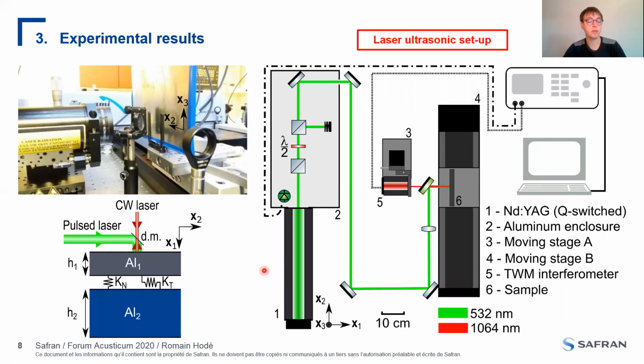To carry out the measurements, we have used this laser ultrasonic setup, which is composed of a pulsed laser here in green with a pulse duration of 10 nanoseconds, and a two-wave mixing interferometer in red that is used to measure the normal displacement of the surface as a function of time.